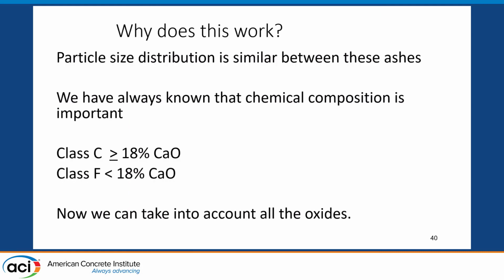And so why does this work? Well, the particle size distribution was pretty similar between all the materials that we looked at. If I use a very coarse ash, it doesn't perform exactly the same, okay? If I use a very fine ash, it doesn't perform exactly the same. But for ones that are traditionally on the market today in this range, it works really well.